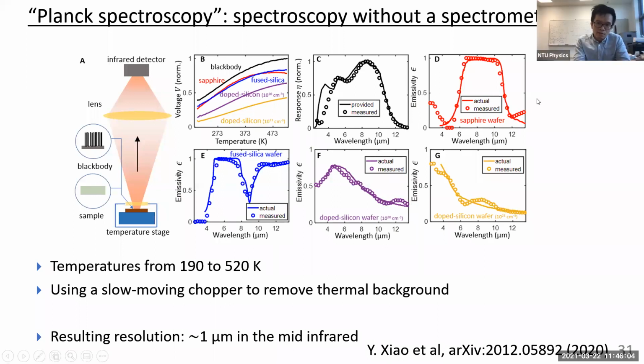It's pretty optimized in MATLAB, right? So maybe we did it as well as you could possibly do it. My guess is somebody using neural networks or something could probably do a better job. But those are actually the only constraints we put on here. You can, in principle, do a lot better if, for example, you assume some shape for your emissivity, like an oscillator model: say there are 3 vibrational resonances and 1 Drude oscillator. Then instead of varying the emissivity at every wavelength, you vary those oscillators. You have fewer degrees of freedom, and it's easier to do the fit. So you can imagine doing better than this.